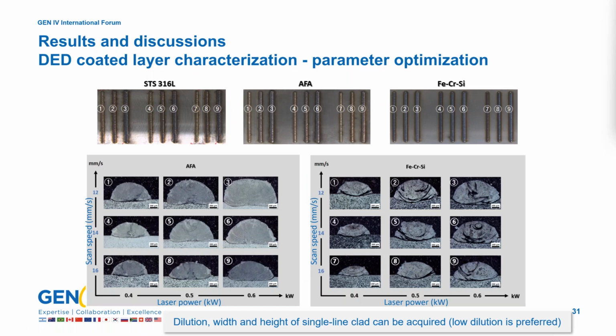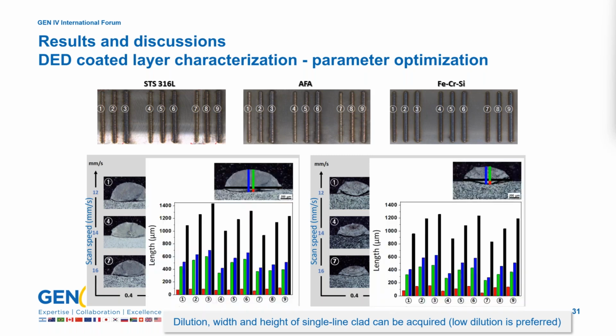From this slide, I will present the experimental results. To determine the optimal heat input conditions for the laser DED process, single-line experiments were performed, and the cross-sections were observed. As a result, the dilution width and height of the single-line clad were measured.